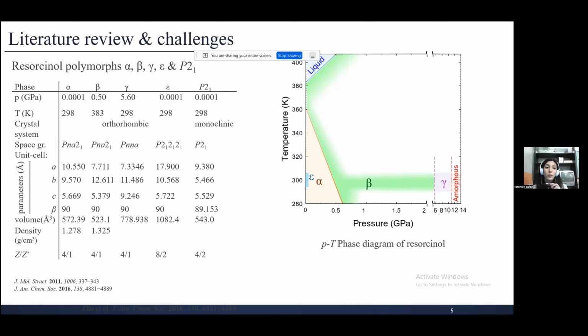But about the gamma phase, which you can see here: in 2011, the Kichanov group compressed beta and claimed that beta transforms to gamma at around 5 gigapascal, but they only reported some unit cell parameters without any structure. And a more interesting structure was epsilon, which was reported by the Bertkan group in 2016.